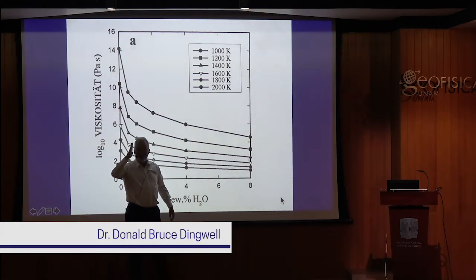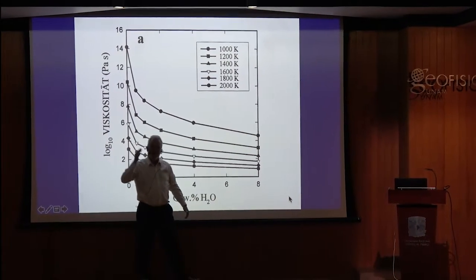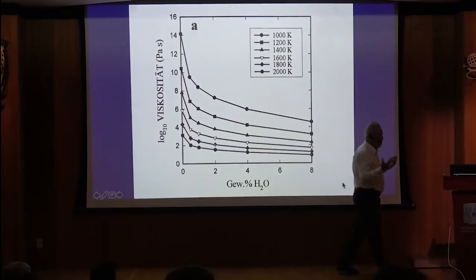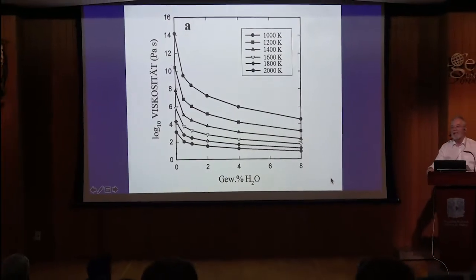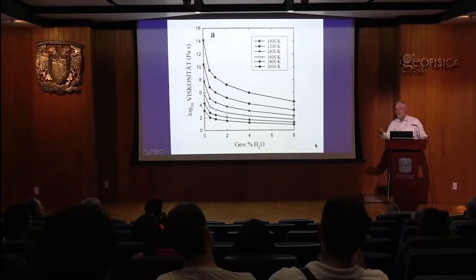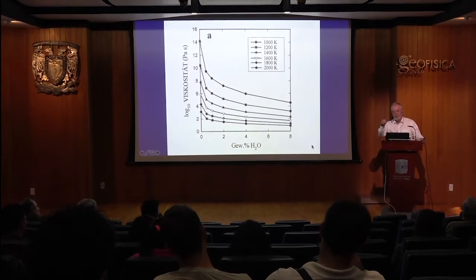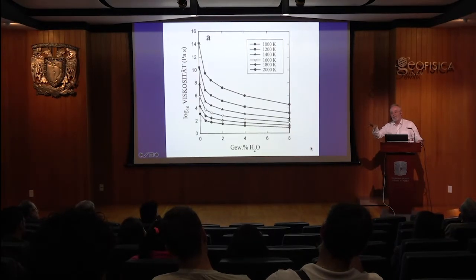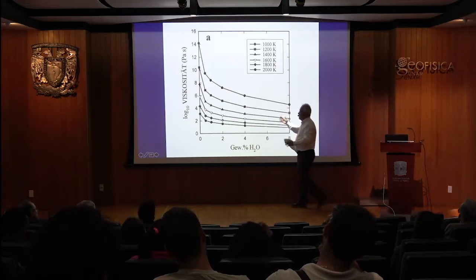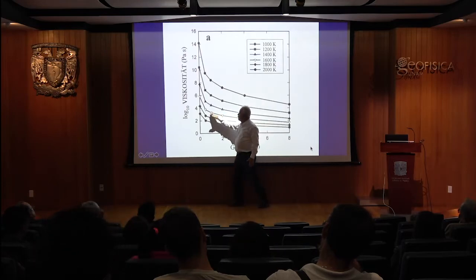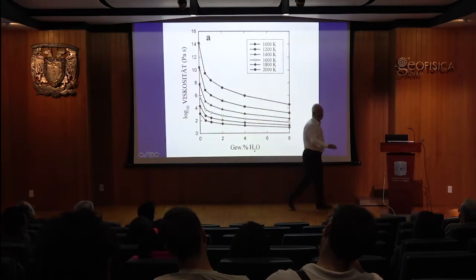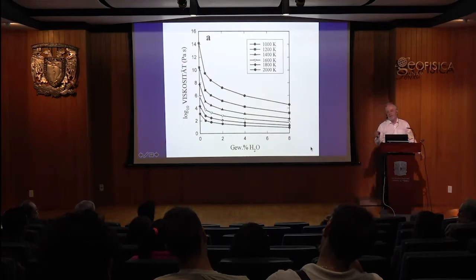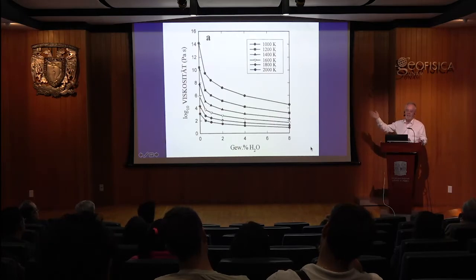And then the yellow line starts to move drastically to higher temperature. I start to make my material be viscous. I start to end up with elastic responsive magma. Because I've moved the water out into the bubbles, it's no longer chemically dissolved in the liquid, the liquid dehydrates, the liquid dries out. And because high silica liquids, this is a calcalkaline rhyolite, show this, we have a crisis, we have a problem, and we have explosive volcanism. Basalt will not do the same thing. And therefore, basaltic volcanism is not largely explosive.